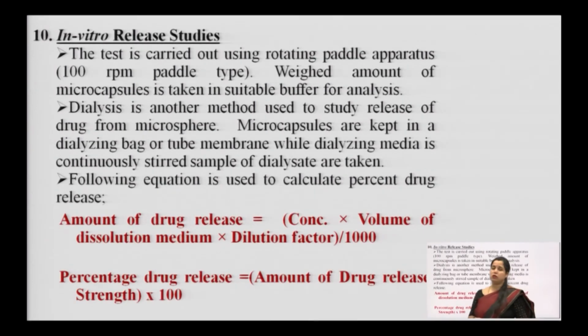In vitro release study is very important, because in case of tablets and capsules you determine dissolution studies, and for microspheres the term is in vitro release. It is all similar, but the procedure is slightly different. The test is carried out using a rotating paddle apparatus as you use for tablets and capsules, with a speed of about 100 RPM, revolutions per minute.